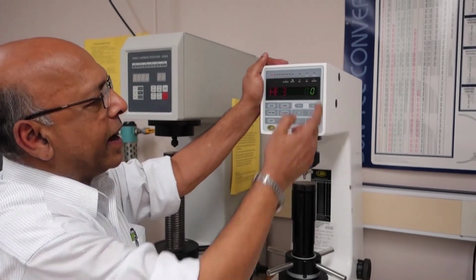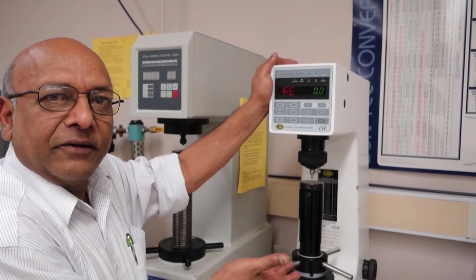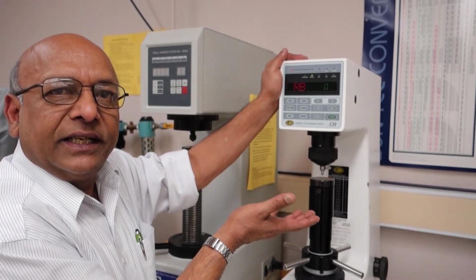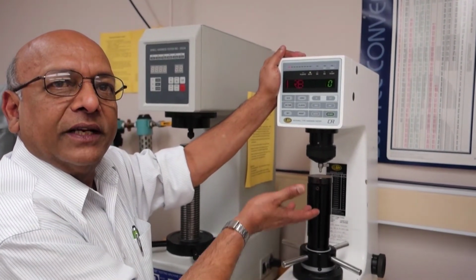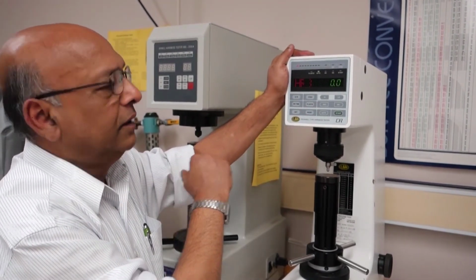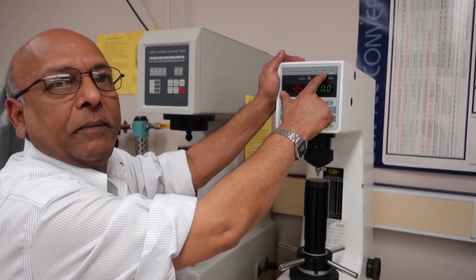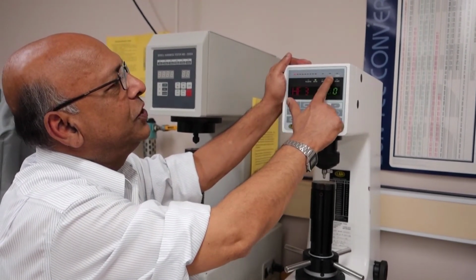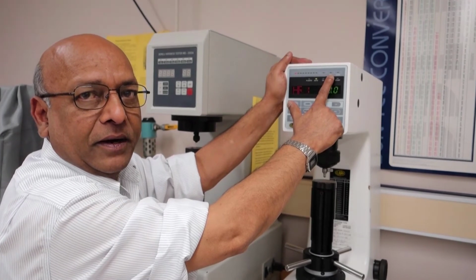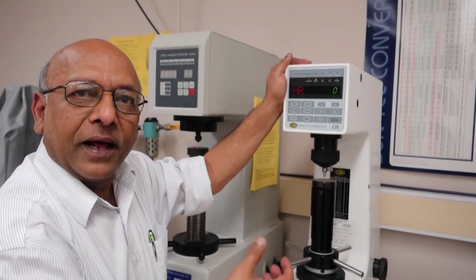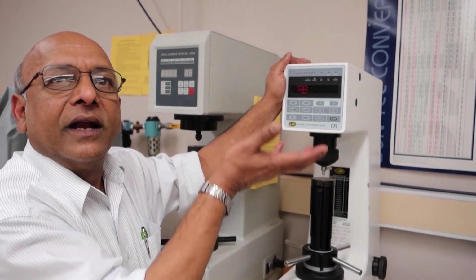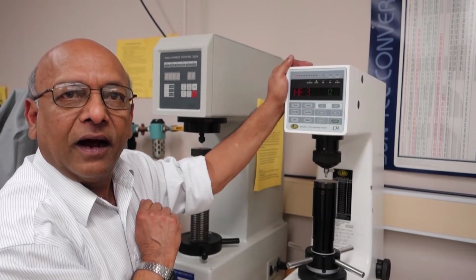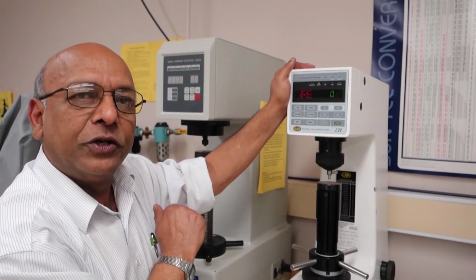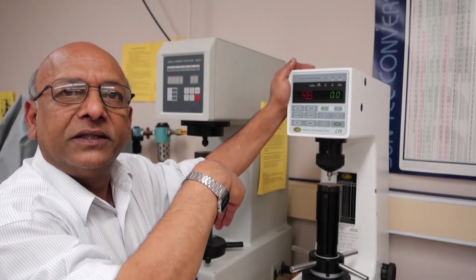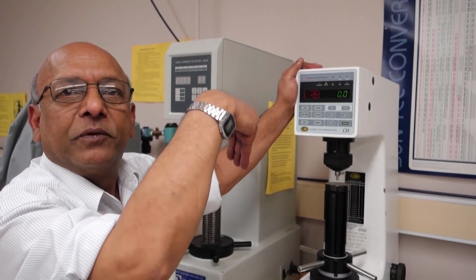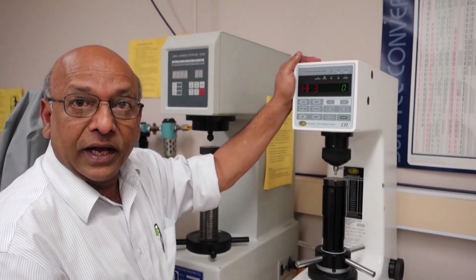On the top we have a band, just like in Brinell hardness testing. I was raising the anvil to seat the indenter. Same way, I'm going to raise the anvil to apply the minor load. Once the minor load is applied and this LED shows me this green set button, the machine takes over, applies the load, dwells on it, and unloads it and displays the hardness reading right away. No measurement needs to be made. The machine makes the measurement of the depth of penetration after the load has been removed.